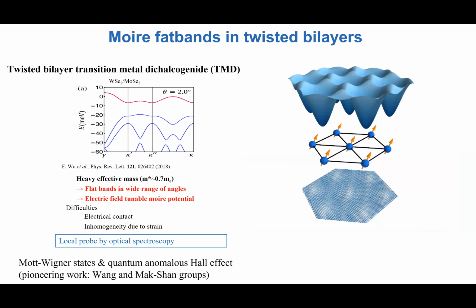So another possibility, though, is that this is not restricted to graphene. One can also take transition metal dichalcogenides, which are semiconducting, so they have dispersive bands, and one can also either stack two of them that have a slightly different lattice constant, or if they have the same lattice constant, introduce a twist angle, and in this way form again a Moire band.